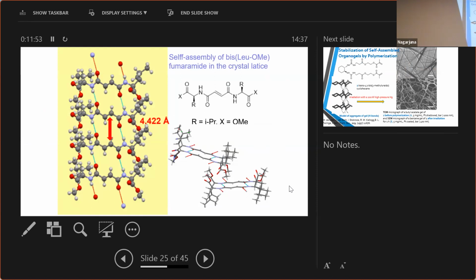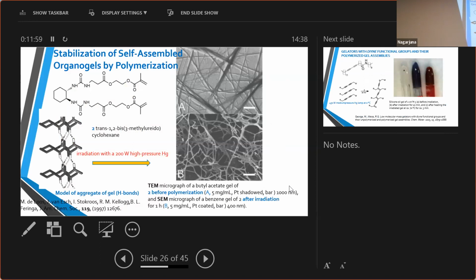Okay, here are a few examples from literature. First is from Ben Feringa. It is work from 20 years ago or something like that. He started with trans cyclohexane derivatives, and they have vinyl esters on the end. When these molecules are similarly connected with hydrogen bonds in gels, and when they irradiate these gels with a high pressure lamp, they obtain a polymerization. And B picture is the same micrograph of benzene gels after irradiation.